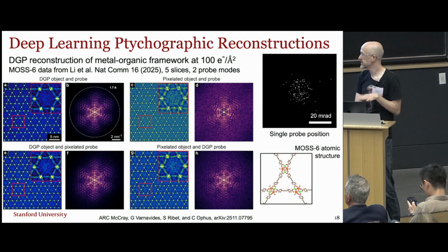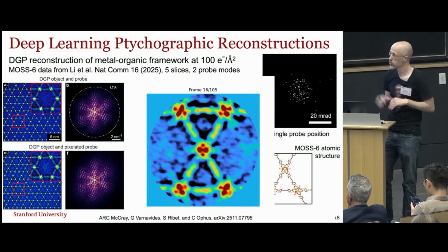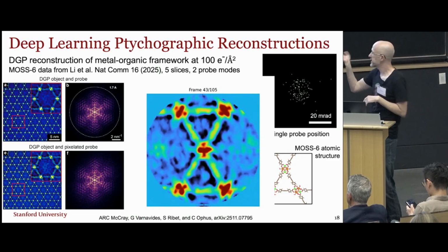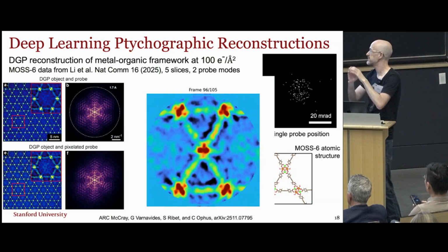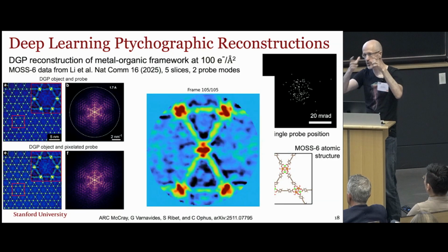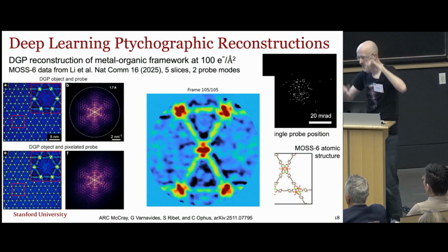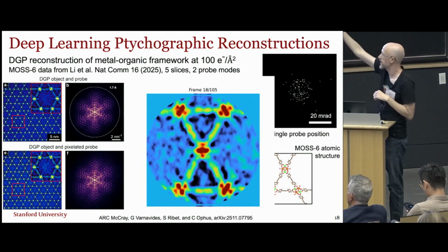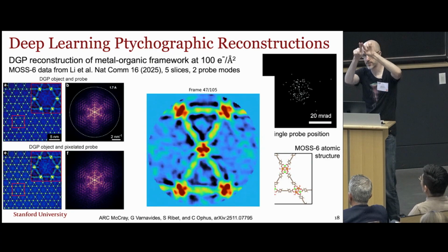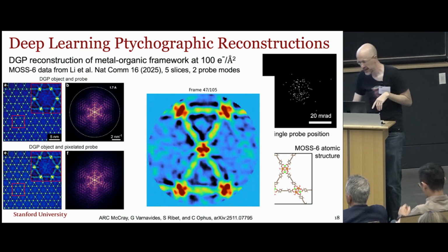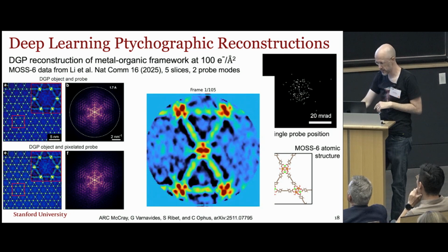And we've compared it using the deep prior on the probe or just the image or on both in the upper left. Doing it on both is definitely the winner in terms of quality. So I just want to loop through all the different structural units here to point out the incredible amount of detail you can see. In these linkers, metal organic frameworks are mostly empty space. That middle dot in the middle is essentially 2 zinc atoms stacked along a column and single zinc atoms, those 4 red dots, with benzene-like rings linking them together in the diagonals. And you can occasionally see in many of these frames sort of the benzene shape, this hexagonal expansion of those carbon rings, right? And that's from data that looks like the upper right here.